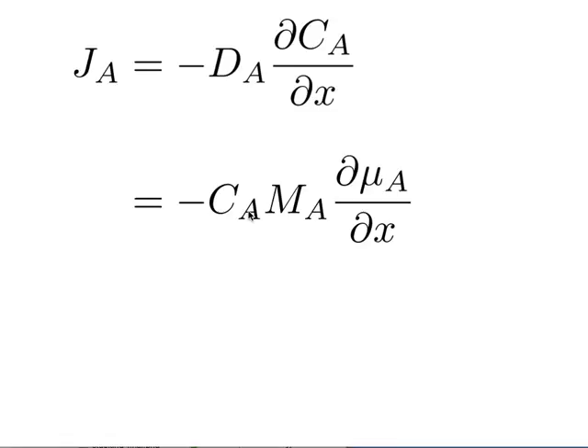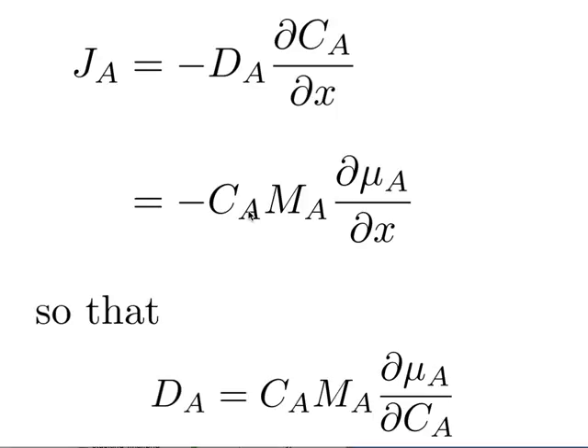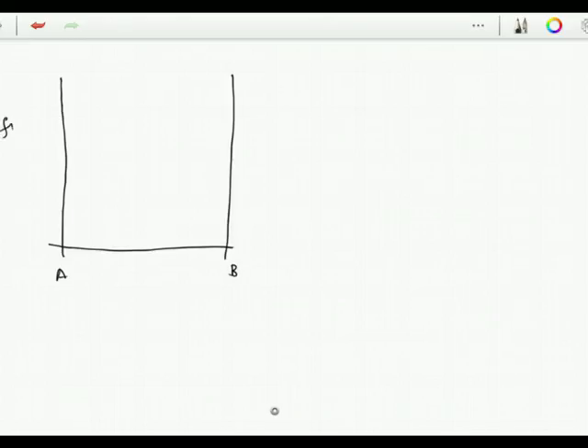Right, so if I compare these two equations, then I can relate the diffusion coefficient to the chemical potential, and that defines the composition dependence of the diffusion coefficient. So if the free energy curve of the solution is shaped like so, where we have A, B, the components, and this is the free energy. And the free energy curve is shaped something like this.